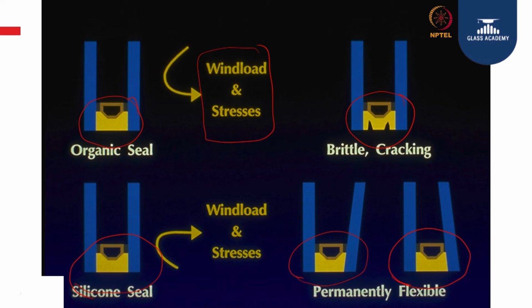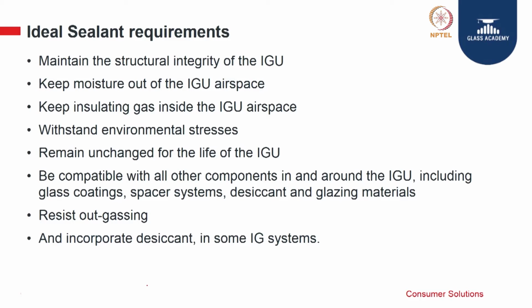Whereas silicone with wind load and stresses has been proven, and the important thing we need to understand is that it allows the movement to happen, either in the form of two units moving together this way or that way, because there is some internal deflection which might happen. Essentially the seal has to keep them tight. Okay. They should not allow the panes to move so differently that it imparts any stress on the primary as well as on the secondary. That is the beauty of silicone. The silicone seal again proves a better product in terms of chemistry than other chemistries.